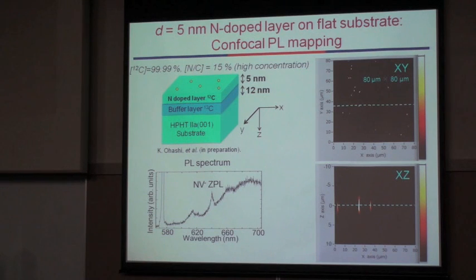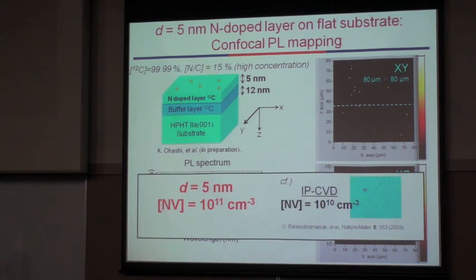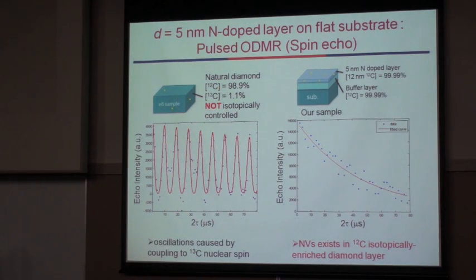So also we can obtain many NV centers in 5 nanometer surface layers. So the concentration of NV centers is much larger than those in isotopically purified CVD diamond. This figure shows a spin echo measurement in the 5 nanometer sample. In this sample, we cannot observe this oscillatory behavior caused by the hyperfine interaction with carbon-13. So this is a confirmation that the nitrogen vacancy center exists in the 5 nanometer surface layer.